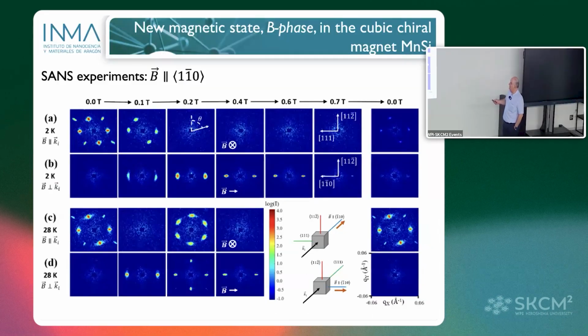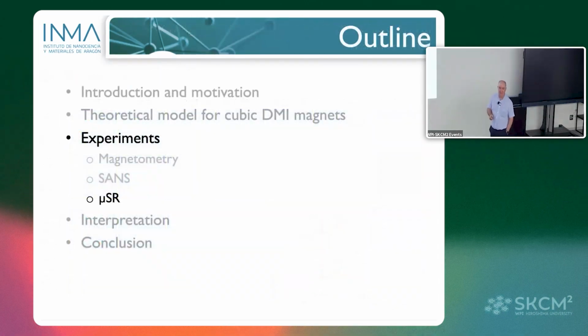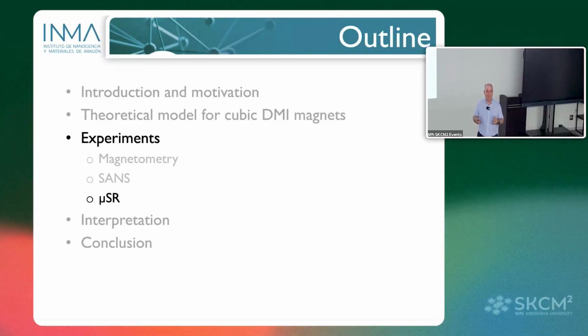You can do the same for other directions, and the behavior is similar. We observe helices, periodicity, but we don't see skyrmions. We don't see skyrmions at low temperature. We see skyrmions only at 28 Kelvin. That means that SANS experiments are not telling us too many things. SANS is telling us that there are no skyrmions at the low temperature. But our SANS experiments are compatible with helices. We have helices and kind of helices.